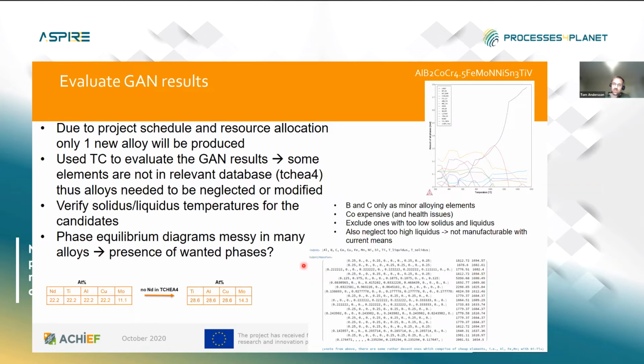And also we took these few elements that are usually used only as minor alloying elements, so that the amount of those wouldn't exceed 5% in the final alloy. And also we further took this cobalt out since it's quite expensive and might cause some health issues. And well, as said, some of the candidate alloys we had to modify a bit because there were some elements missing from the database.